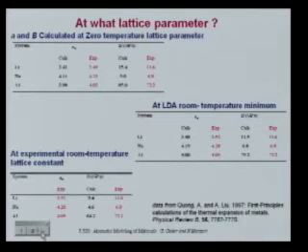So here, the bulk modulus is calculated at the zero temperature lattice parameter. That's what you would typically do. Say for lithium, the lattice parameter that you calculate, this is in LDA, is 3.41. And you get a bulk modulus that's 15.4 gigapascal, and experimentally it's 11.6. Okay. Just like you expect, it's too stiff, very typical in LDA. Same deal for the other metals, although for aluminum it's not as bad.